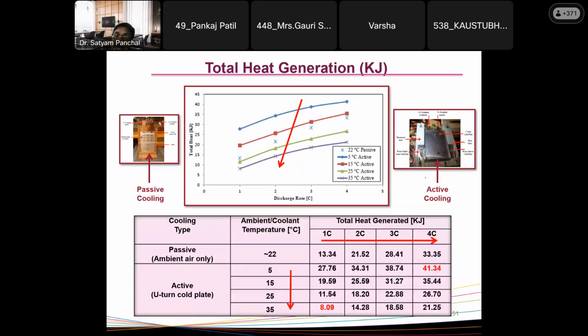And again, heat generation was measured for air cooling as well as for water cooling at 22 degrees, and for water cooling at 5, 15, 25, and 35 degrees, at different C rates of 1C, 2C, 3C, 4C. And it is concluded again that for water cooling, the highest heat generation was at 5 degrees and 4C, and the lowest heat generation was at 1C and 35 degrees C.